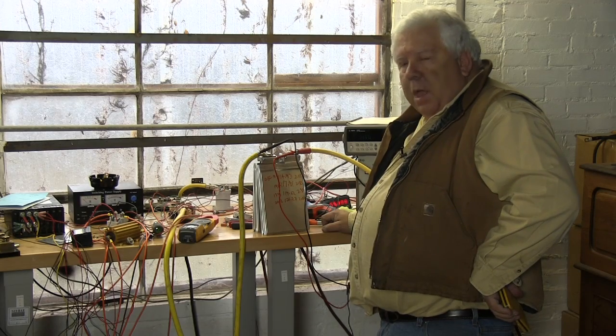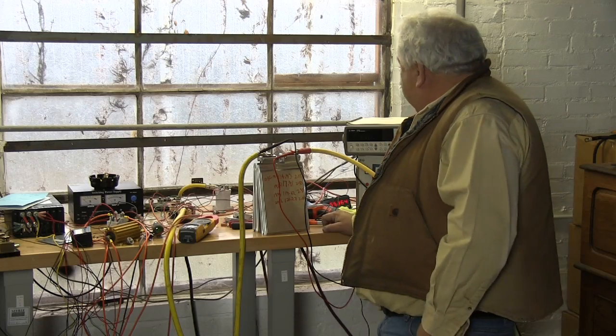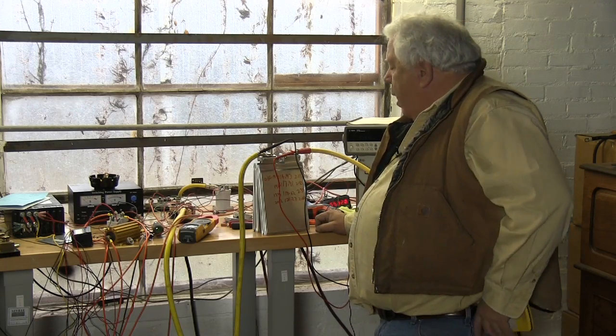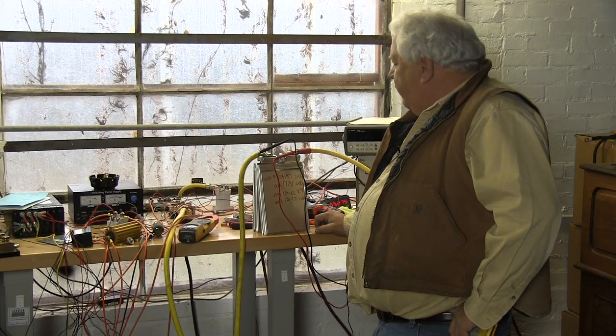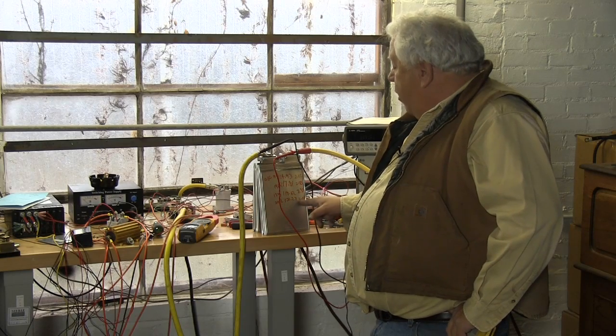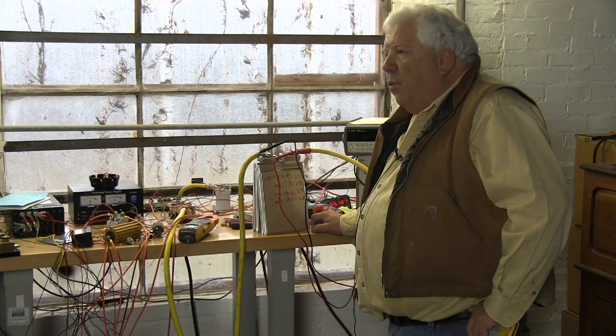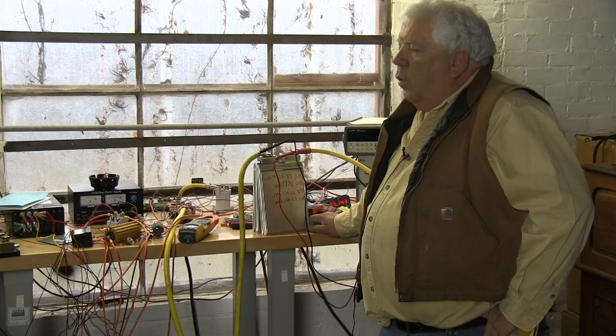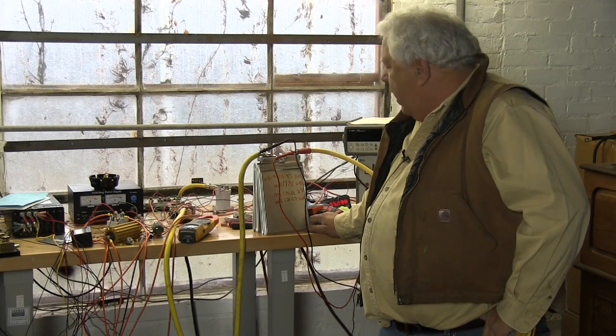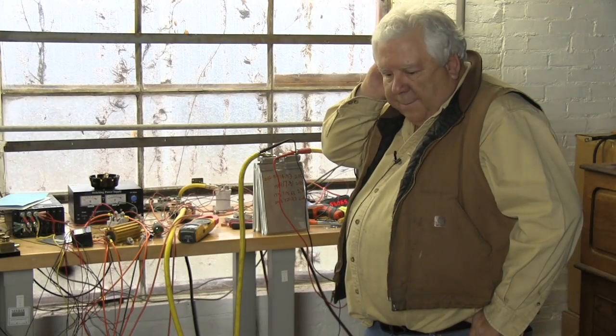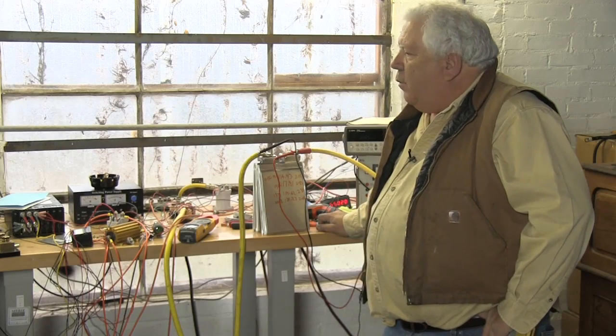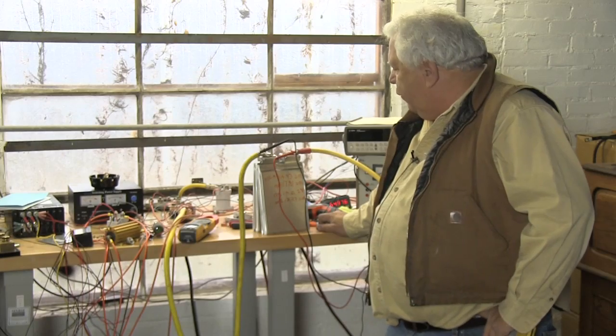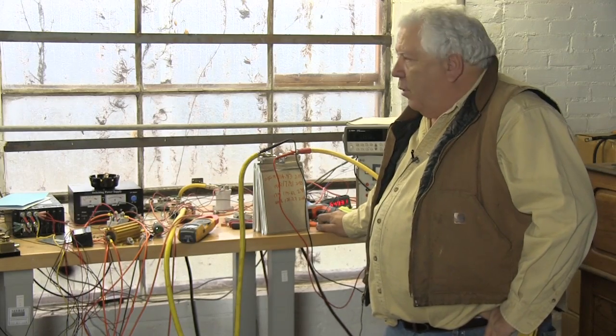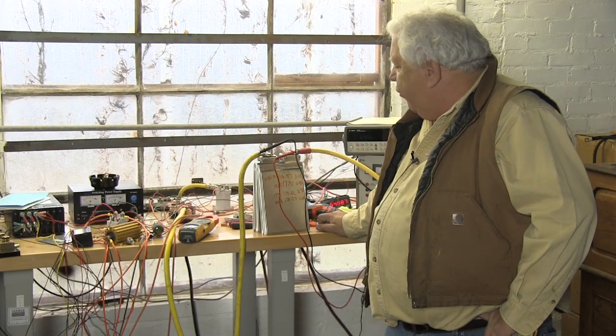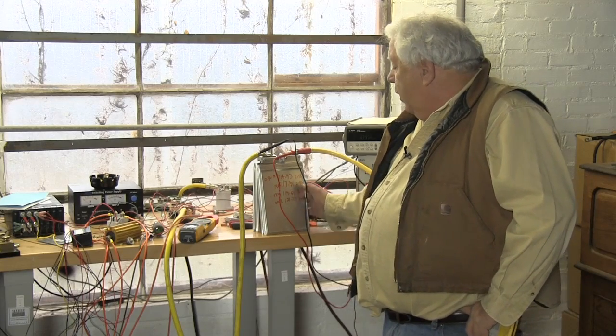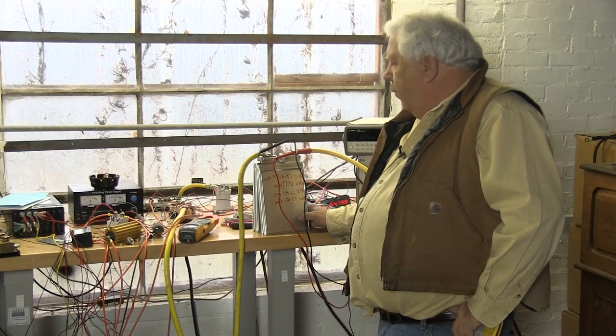From what I can see here, we'll continue to use 2.5 volts as the cutoff for these A123 cells on the low side. On charging it, we got up to 3.65 volts at just about an amp hour shy of our 2.5 volt discharge, and we were right at 3.65 volts and had diminished to 6 amperes, which is 0.05 C, and that's the normal Thunder Sky variables we use, and they work very well for these A123s. We're not going to charge them any higher than that. We're going to use 3.65 per cell, maybe even 3.5, and in all cases call 2.50 volts the